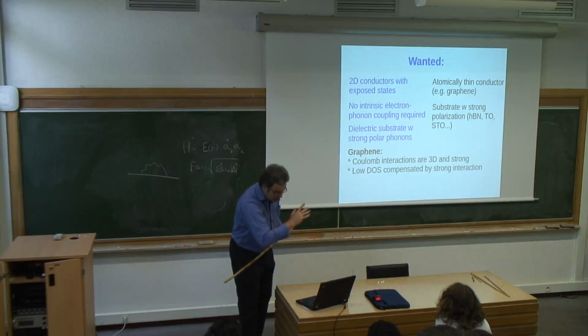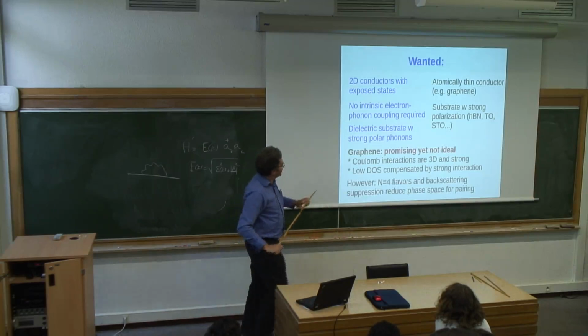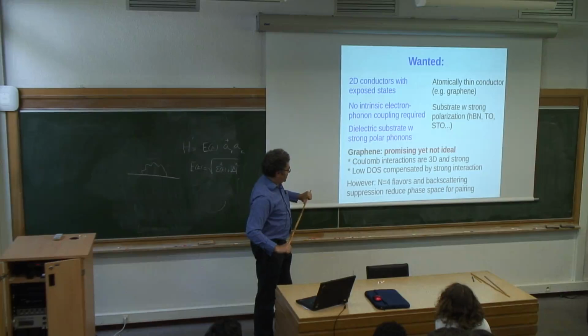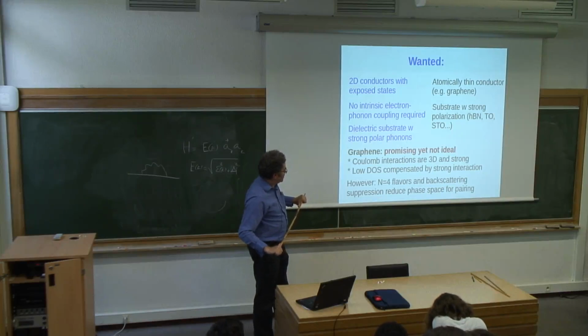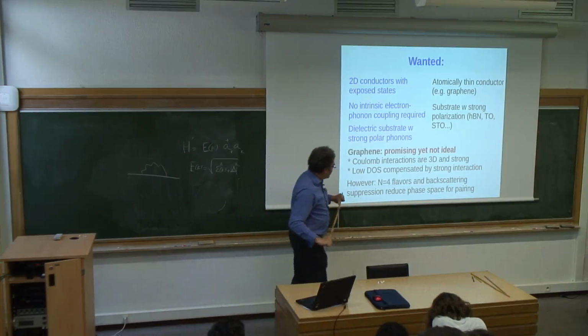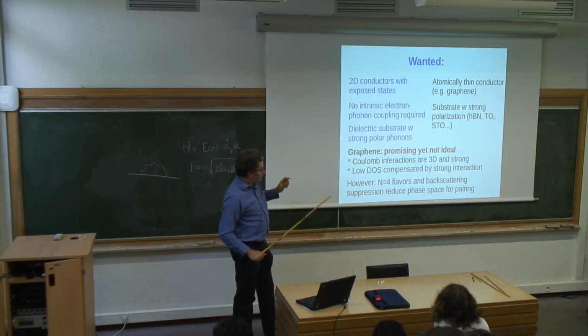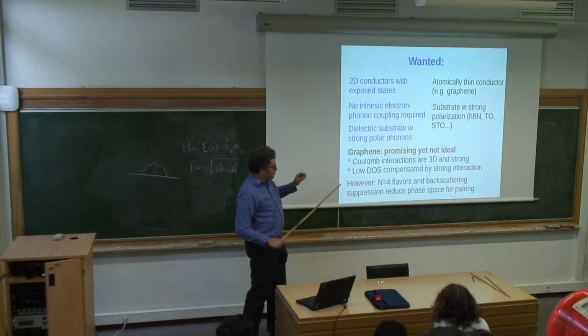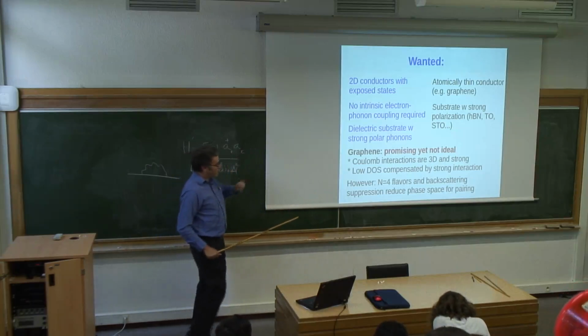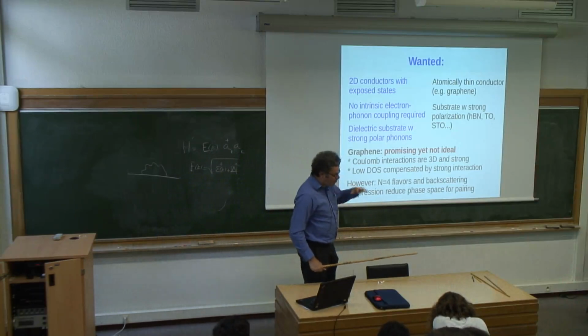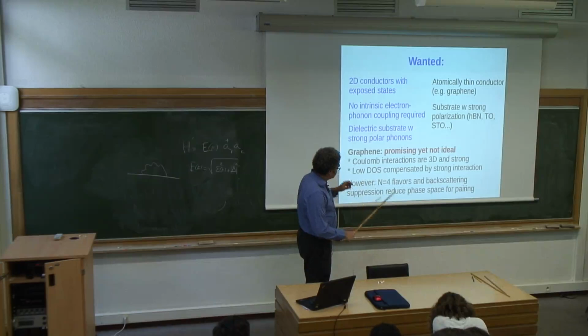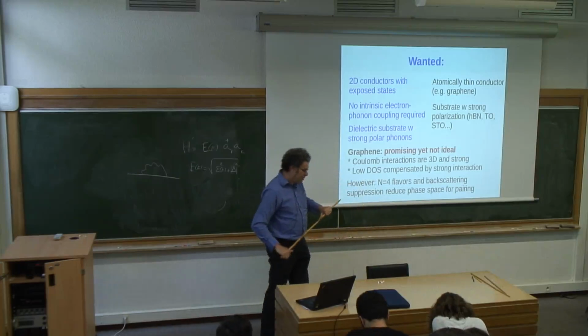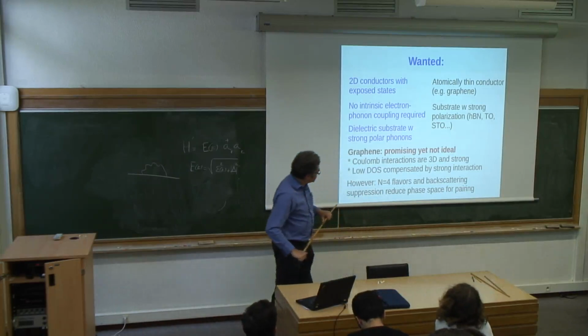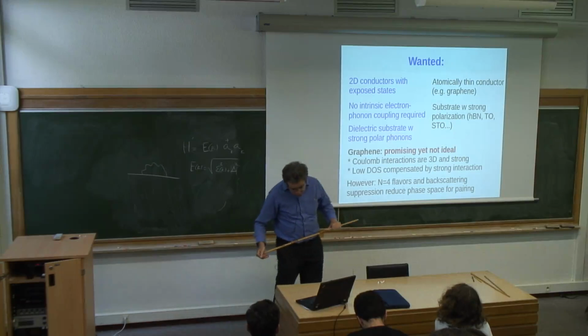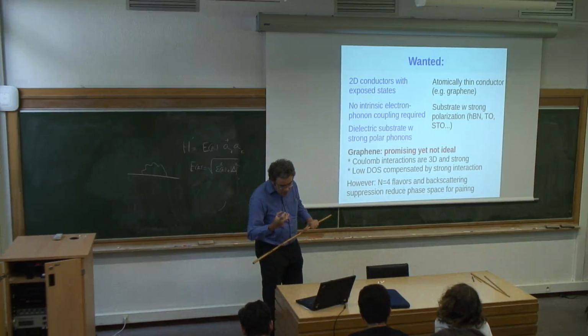Right. So for graphene there is good news also, but if you start calculating, you find that it's not entirely sunny. You have 4 flavors, and you can only have pairing because you have this K minus K constraint. You can only have pairing between states with time reversal symmetry. So you lose about half of your states because you have 4 flavors rather than 2 flavors as you would have if you only had spin as degeneracy. Also, you lose some of the phase space because of backscattering suppression, Klein tunneling, if you wish, and so your effect is